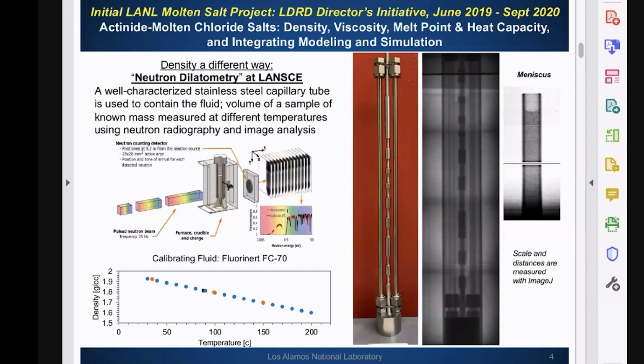And so the first stuff I wanted to talk about here was what Jake was mentioning earlier, which is using LANSCE. So this is a neutron beam. It's a very unique capability that we have on site at Los Alamos. I really want to emphasize that this is on our site, so it makes it very convenient for us to just prepare samples and drive them over and study them at the beam. Another really unique capability there at LANSCE is that it has the ability to look at actinide samples, up to and including plutonium. And then another thing we recently found out is that we can also place irradiated samples into the beam. So this is just a great opportunity that we wanted to take advantage of, and I believe we did pretty good with this, and we're continuing it on now.